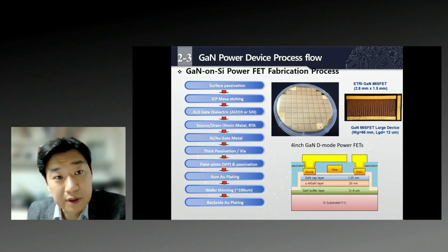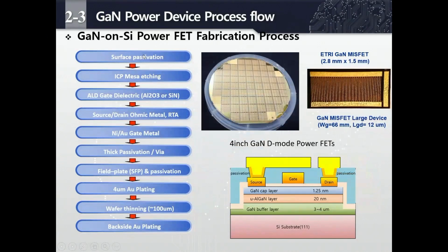The process of the gallium nitride power device is quite similar to the RF device. The main difference is that we are using GaN on silicon instead of GaN on silicon carbide, and also we are using field plate structures to make a high breakdown voltage. And this is the fabricated 4-inch gallium nitride D-mode power FETs, and here are the gallium nitride MISFET diced structures.